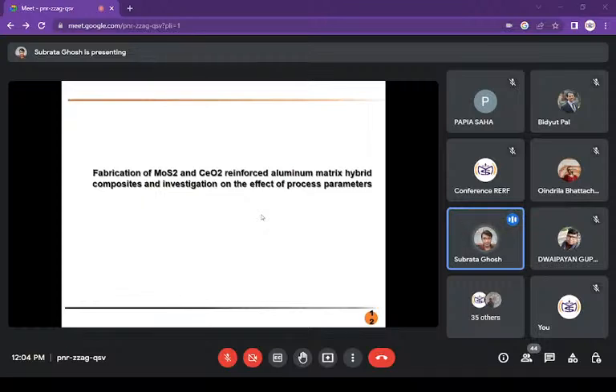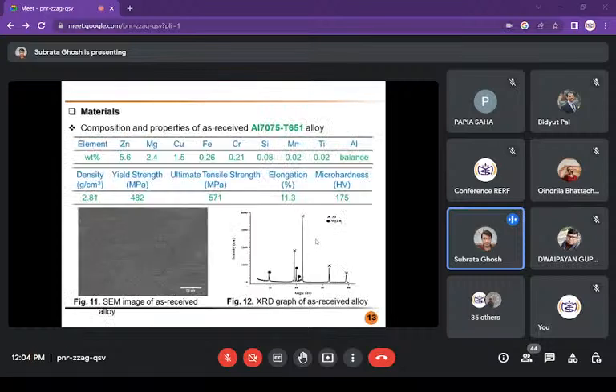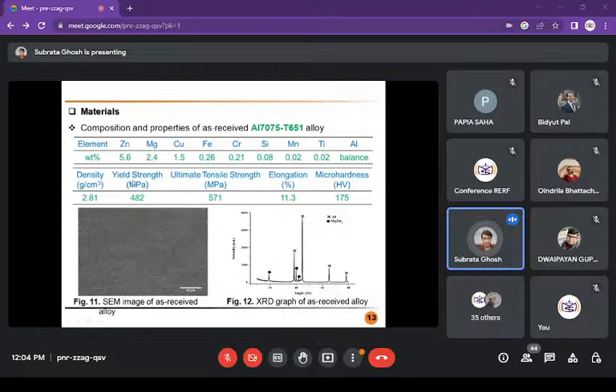This is the fabrication of MoS2 as well as cerium oxide reinforced aluminium matrix hybrid composite, and investigation on the effect of the process parameters. The alloy material I have chosen here is aluminium based, the 7075 alloy. The elemental composition is also highlighted here, and the properties: density, yield strength, ultimate tensile strength, elongation, and microhardness are available for this material.